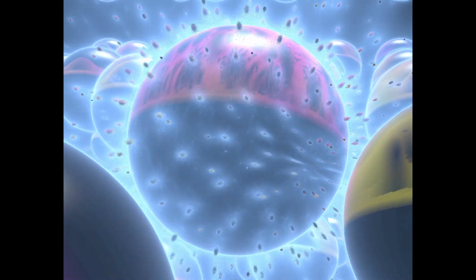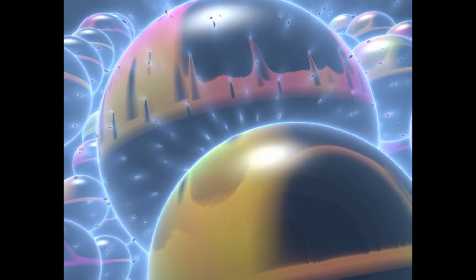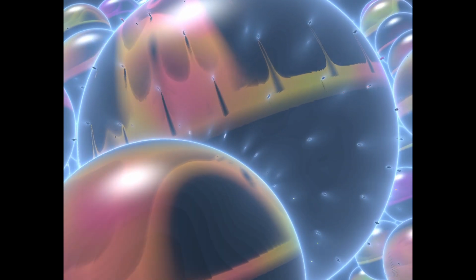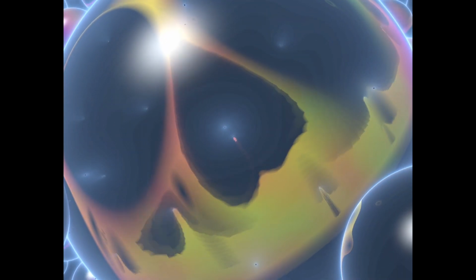First, they calibrated their setup with a microscale diamond, essentially setting a baseline for comparison. Then they swapped in the nanoscale diamond, keeping everything else the same. A classic controlled experiment. So they were comparing apples to apples, or rather diamonds to diamonds. What were the results? Did they manage to overcome that diffusion barrier? The results were astounding. They achieved single-digit Hertz resolution in the nanoscale NV-NMR spectra of water.